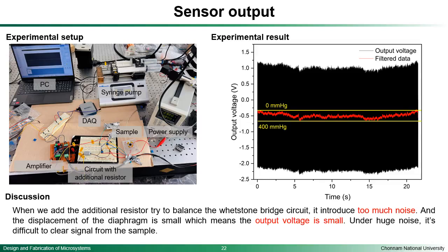Then we connect our sample to the circuit with additional resistors and an amplifier. The signal goes through the DAQ and we can see our data on the computer. We use a syringe pump to give some pressure. When we look at the experimental data, because we applied additional resistors, this introduces a lot of noise. And due to the diaphragm thickness issue, our output voltage is not very high. So for these two reasons, we can see just a little change of the voltage, but the noise was too high.